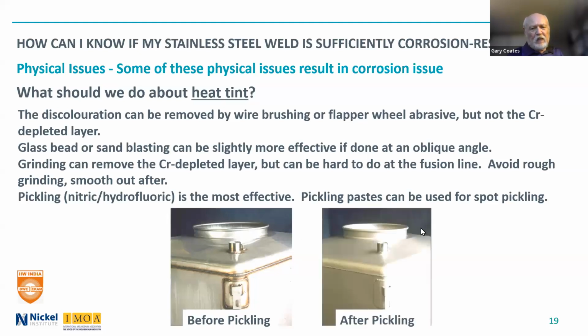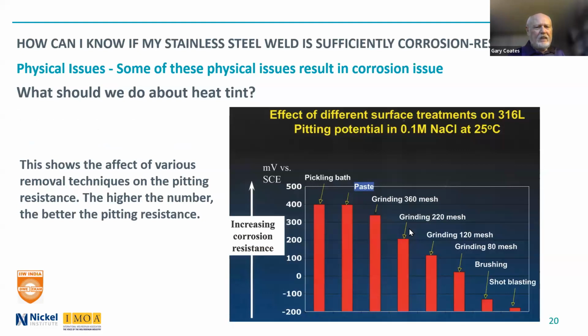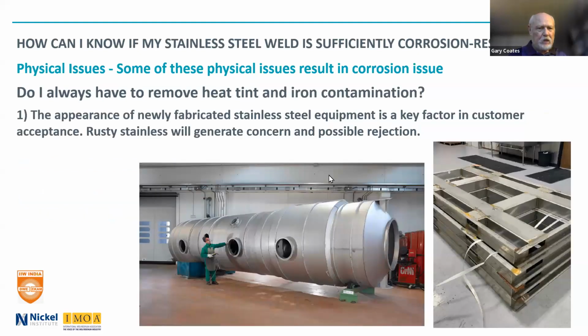There's just the typical before and after pictures for pickling. And again, this graph, and I've shown it many times, talks about the comparative resistance to corrosion, specifically pitting resistance, of the different surface treatments. With shot blasting, in this particular case, they actually blasted the material into the material. It wasn't a glass bead blasting. Brushing, grinding with the different roughnesses, and the 360 mesh, the finest grinding, was the best. Pickling paste and pickling bath are both excellent ways of getting the optimum corrosion resistance from the material.